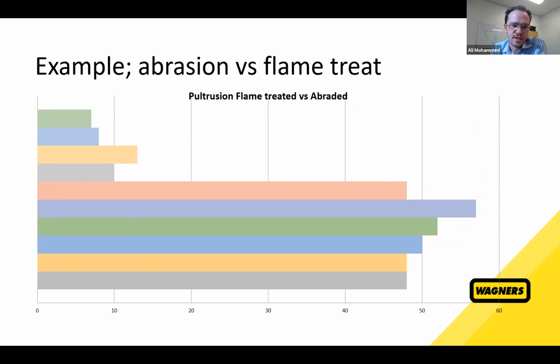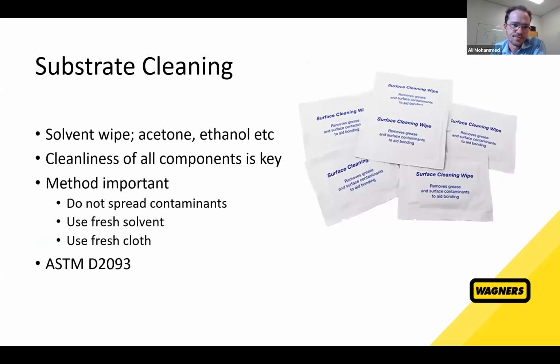Here's another example of something we've done in-house, whereby we looked at abrasion versus flame treating. On the bottom is the abrasion, so you can see that for us, abrasion doesn't give a massive benefit in terms of better wetting or higher surface energy, but for us it helps with cleaning the surface and removing contaminants. And obviously the top is the flame treat, so we get a very good result from flame treatment and see very, very low contact angles. So yeah, we get great benefit from flame treating for our bonding processes.